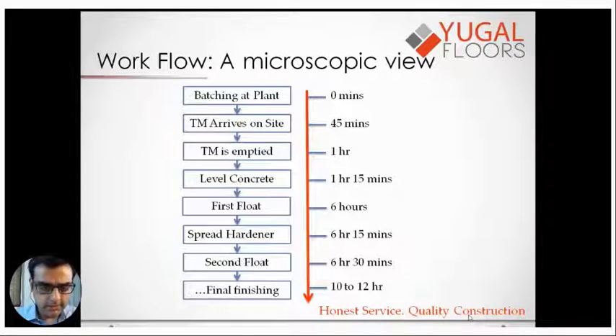We spread the hardener. It takes us about 15 minutes to spread the hardener. We do a second float that takes us about 15 minutes, and the whole process takes about 10 to 12 hours. So the message here is, we work on this concrete for a period of about 10 to 12 hours, and there are several steps involved, and these steps have a set sequence. One step comes after the other. We cannot mess around with this sequence. And if you're following Dr. Wish's presentation, he mentioned the moment the cement and water come in contact, the clock starts ticking.